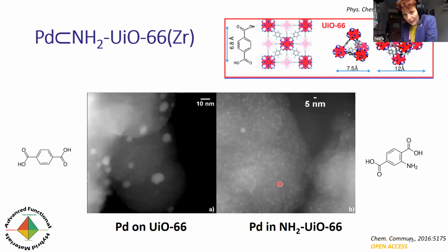So this is an ADF STEM micrograph of the palladium amino UiO-66. And you can see that we have well dispersed palladium particles. They are the bright spots of sizes either 7 or 11 angstroms. So this is a very good agreement with the pore sizes of the framework. So we knew that these are very tiny.